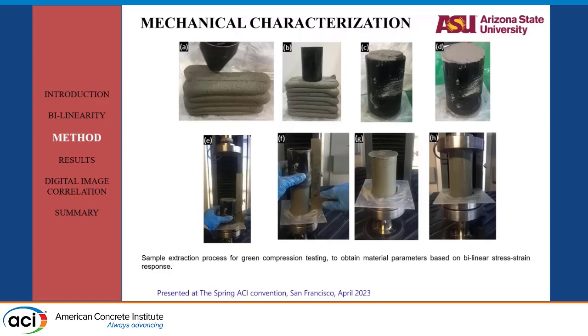And once inserted, we removed the outside printed material and we smoothened the top surface. We removed carefully the top surface so that the top surface is smooth. And we put a right angle, 90-degree angle such that the cylinder remains vertical when it's taken out of the mold. And we put a glass plate on top of it such that the whole cylinder is loaded.